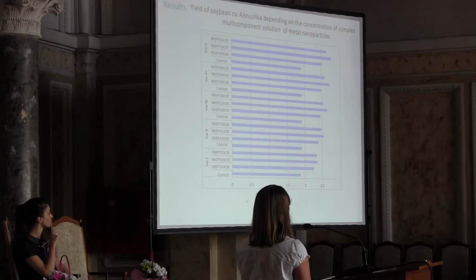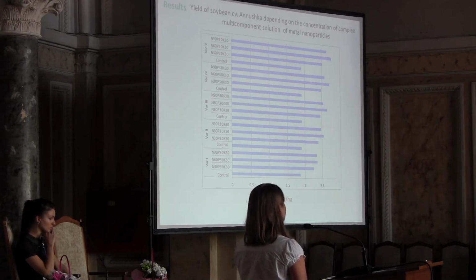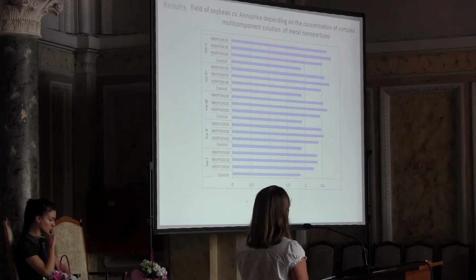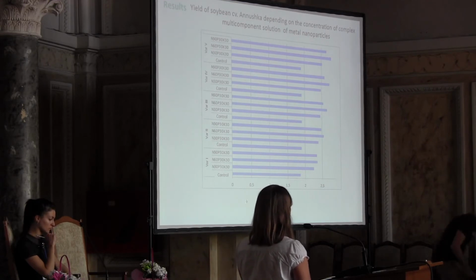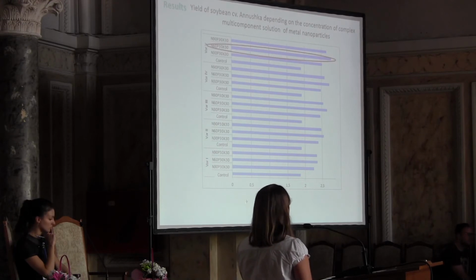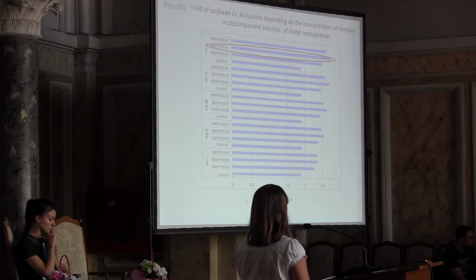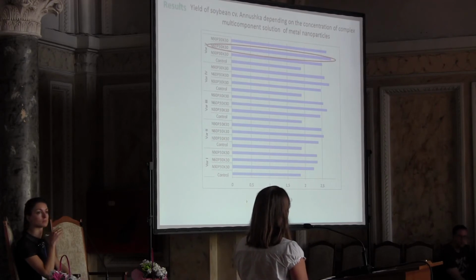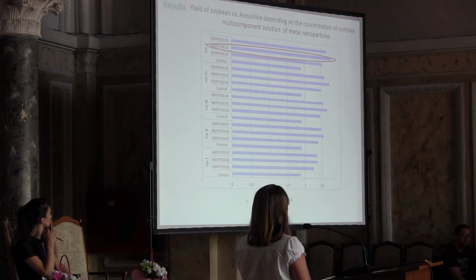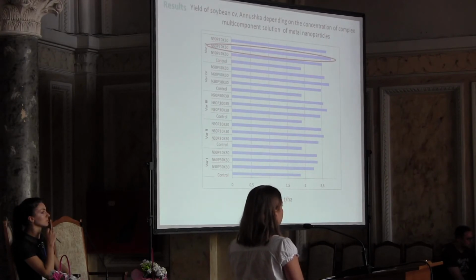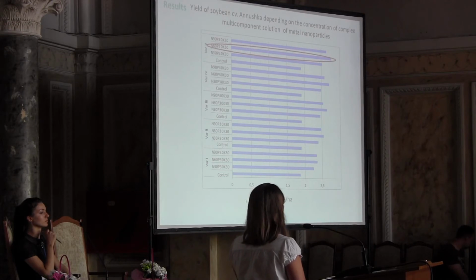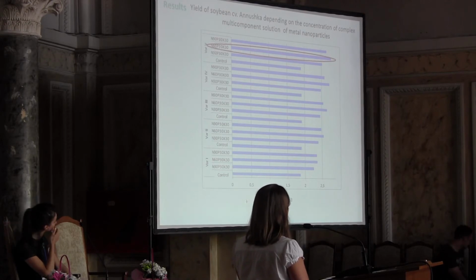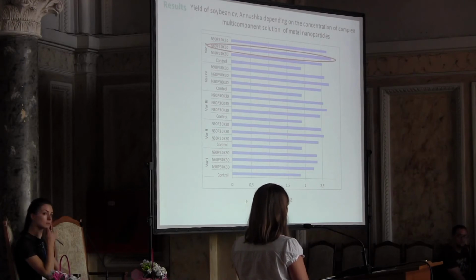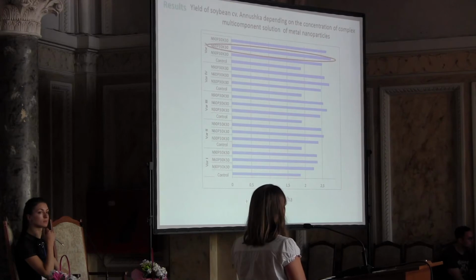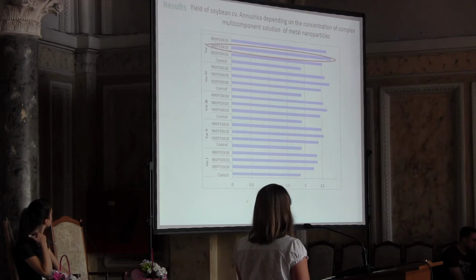Yield of soybean of cultivar Anushka depended on the concentration of the complex multi-component solution of metal nanoparticles as well as the nutritional rate. But the highest productivity of soybean was obtained after the double treatment by a complex multi-component solution of metal nanoparticles. It was pre-sowing seed treatment and foliar spraying by solution in concentration 240 milligrams per liter, and the highest yield was obtained with a nutritional rate of nitrogen 60 kilograms per hectare.